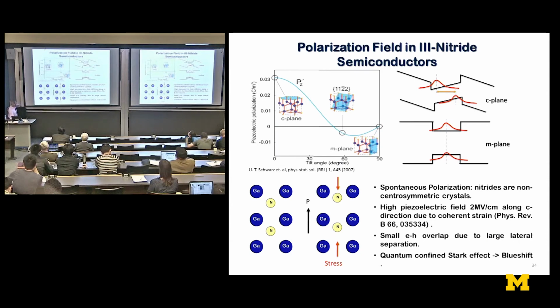Now, in the nitride materials, there is a problem. In the C-axis, and most of the work is with C-plane nitrides, you have a very large polarization field, and there's spontaneous and piezoelectric polarization. And that means that the heterostructure band diagram looks something like this, and the electron and hole wave functions are inherently separated. This results in large lifetimes and very poor quantum efficiencies.